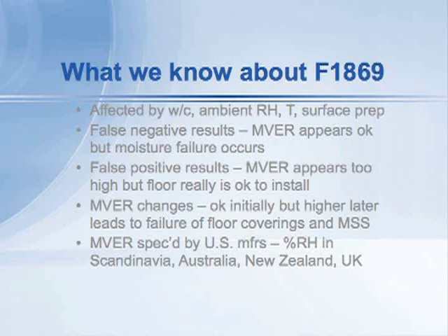You can get both false positive and false negative results — high results and low results with this test that are not very useful. We also know that moisture vapor emission levels tend to change. You might measure a floor today and then put flooring down, and if you have a failure, many times we've seen that you come back and repeat the test and you get a higher value later on. That's because moisture within the floor has come up near the surface. So it's a test that changes depending on how the moisture picture within the slab changes. Any test that gives different results depending on the weather, the temperature, and the particular day you do the test is fundamentally going to give you not very useful information.